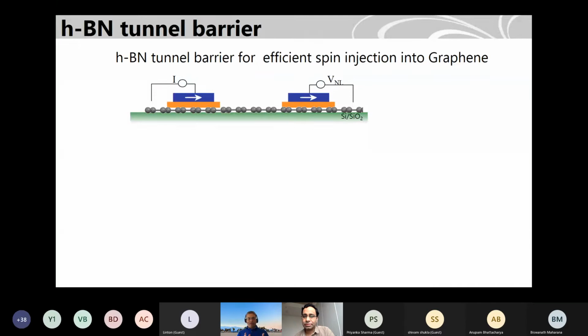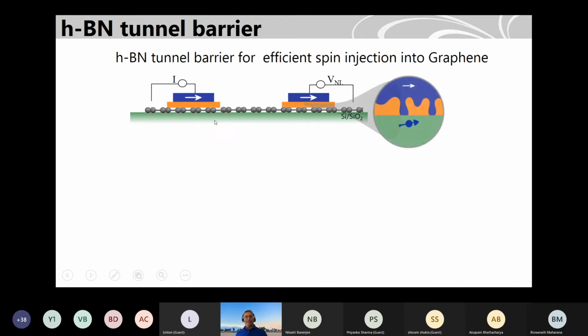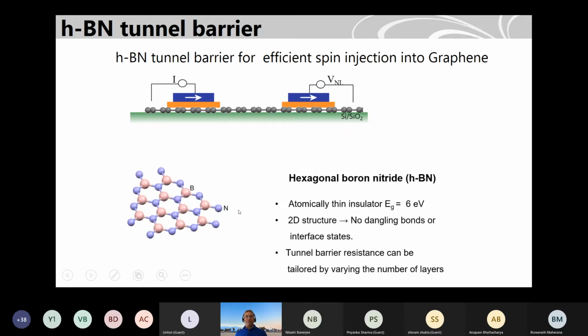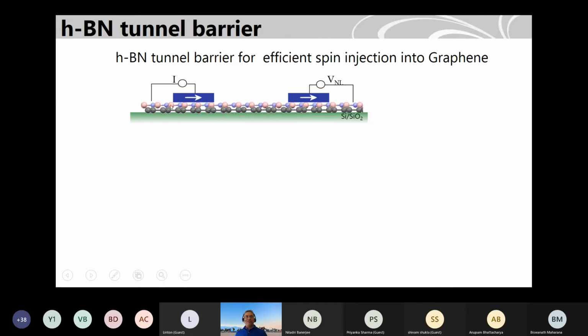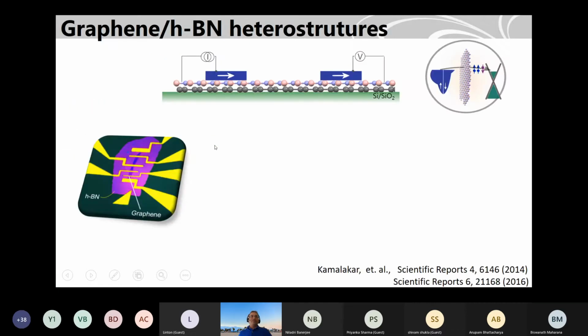So I showed you how boron nitride can be interesting for encapsulation and getting high quality graphene. Also, boron nitride can be a good tunnel barrier and also good for spin injection into graphene. As you know, we use a titanium oxide tunnel barrier, so it's not very perfect and it has pinholes because you cannot grow a very thin oxide layer on graphene. So the pinholes can also affect the spin transport or spin injection into graphene. So if we use boron nitride instead of titanium oxide, this can be quite good.